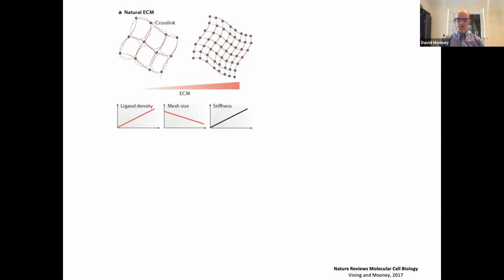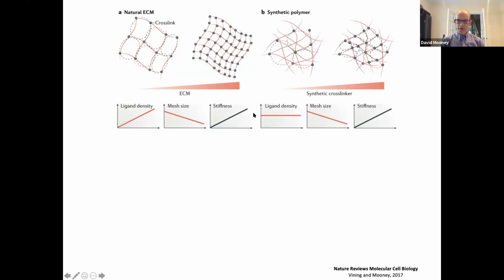With these natural materials, it's difficult to do real cause and effect kinds of experiments. Now one can, in contrast, instead use synthetic polymers to form hydrogels, and here keep the polymer content the same, utilize polymers that don't mediate cell adhesion, but then you couple small peptides that mediate adhesion, so you can keep the ligand density constant as you vary the cross-linking and change the stiffness. However, in this context, the mesh size also diminishes as the stiffness increases. So we have coupled mechanics and diffusional issues with the gels.